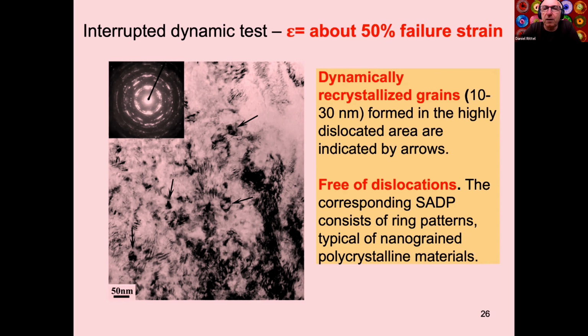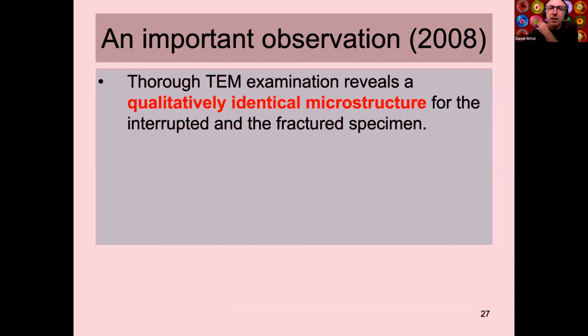Then such grains are, in fact, producing the shear band because, on the one hand, nanograins, they are stronger than the surroundings. That's the whole Hall-Petch effect. But on the other hand, they have absolutely no hardening capability. That was shown already long ago by my friend, Professor Ramesh, who's here with us today, who showed a series of beautiful papers, and one especially on iron, coarse grain and fine grain. And he showed that the fine grain, ultrafine grain iron was prone to shear localization with very little strain hardening. So here you have the same thing, in fact. So this specimen did not fail, and well, qualitatively at midway to failure, we already have the final microstructure.